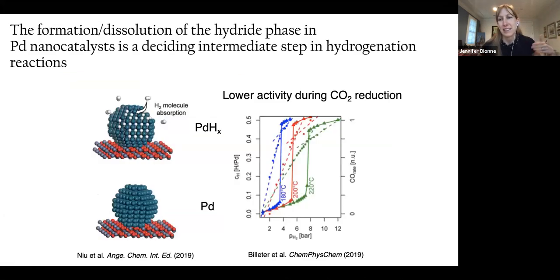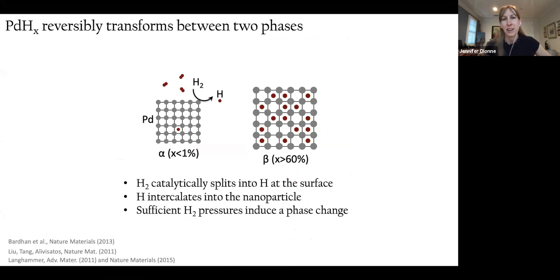And in the last 10 years that I've been at Stanford and developed methods within the electron microscope, we've started off with a model reaction that's the hydrogenation of palladium. And the reason for that is because it's not only a very historical and well-studied model system, especially in bulk, but it turns out that the formation and dissolution of the hydride phase in palladium catalysts and at the surface of these palladium catalysts is often a deciding intermediate step in many catalytic reactions that are hydrogenation based.